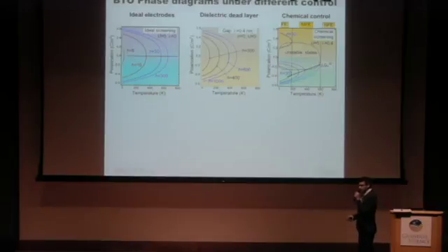But now let's look at the more interesting case where we have this electrochemical boundary condition. At high temperature, of course, it's paraelectric. You see nothing. At low temperature, there is a polarization that's stable here, and a polarization stable here, so that checks out. But in this intermediate range between 200 and 600 Kelvin, you can see that there's a large region where there's only one stable polarization state.